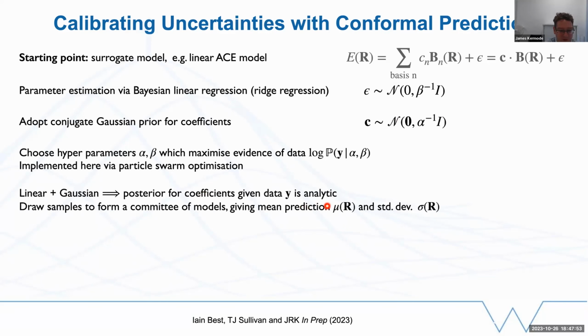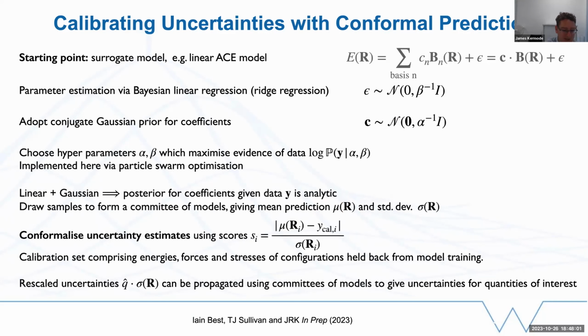And from those models, we can form a committee that gives us both a mean prediction that we can use as our central estimate and a standard deviation across the members of that committee. And then we can use this conformal prediction idea to rescale those errors, so to compute these scores, which say how far away is a particular mean prediction from the true calibration result, and what's the associated error with that, and then use this rescale factor to scale up or scale down those uncertainties.